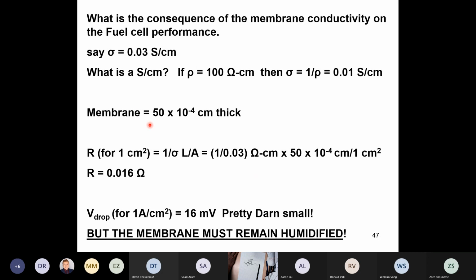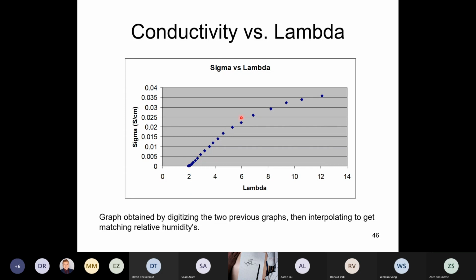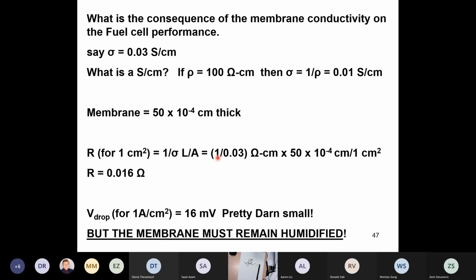So we have a 50 micron membrane, and you want to know the resistance per centimeter squared. Resistance is resistivity times the length divided by the area. So the resistivity is 1 over sigma. You put that in, you work it out, and you get 16 milliohms as the resistance. So if you're running 1 amp per centimeter squared, a typical current density for a fuel cell, it gives you a 16 millivolt drop in the membrane. That's pretty small, and that's good. But if the membrane dries out, then you're in deep trouble, because then the resistive drop in the membrane is enormous. So the membrane has to remain humidified for decent fuel cell operation.